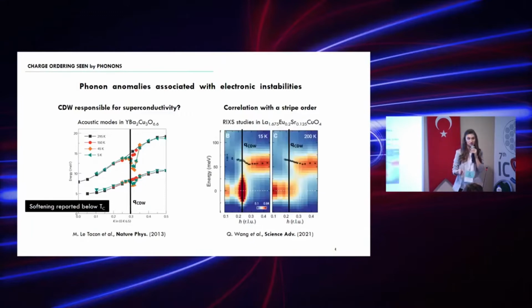Also, more recent data are showing similar results. These are RIXS studies performed by Johan Chang's group, and it was also done for a striped system, lanthanum europium copper oxide, and also around QCDW a softening of a high-energy phonon mode was shown. However, RIXS studies are limited because of their resolution. The resolution is in the range of tens of millielectronvolts. We know other techniques that can also explore phonons more carefully.